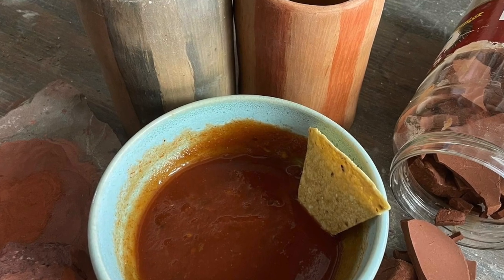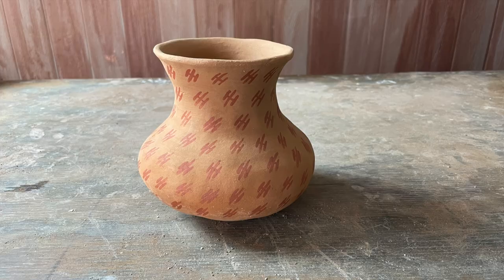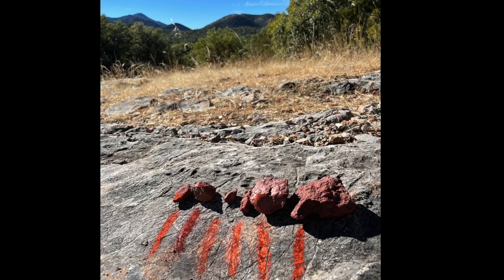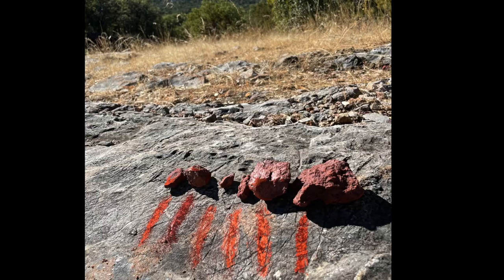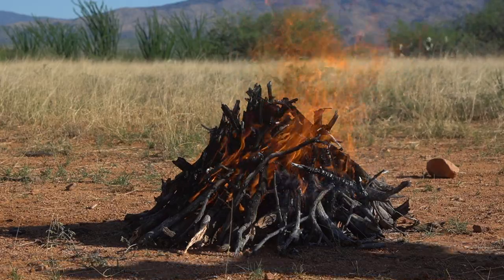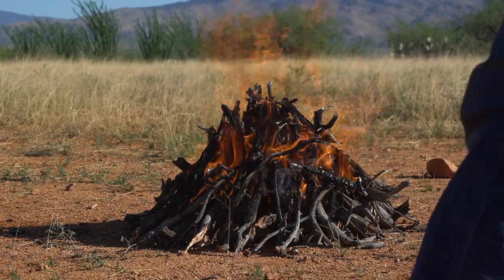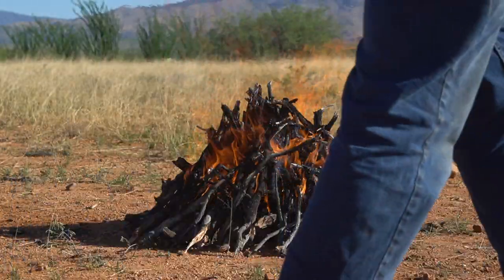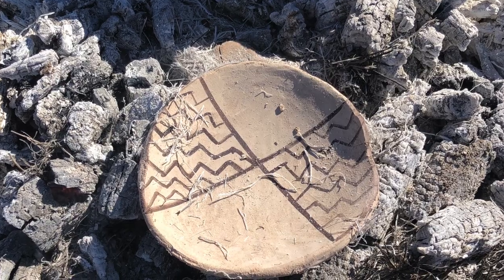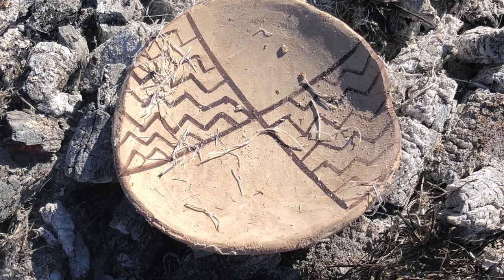I have a lot of experience with red paint recipes — I've made a lot of Mogollon red-on-browns, even some Hohokam red-on-buffs. Red paint is something I can do: that's just red iron oxide mixed with red clay, about two-thirds red iron oxide and one-third clay. I know from experience firing with these red iron paints that if I fire hot enough, say over 800 degrees Celsius, even in a surface fire with lots of oxygen flow, those reds will turn black. When you open that up and start pulling pots out, they will be black, and then they will slowly turn red as the pot cools. So I can reduce red iron oxide — the real secret is how to keep it from turning red as it cools; you've got to somehow remove it from oxygen.